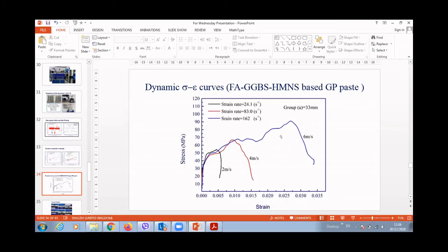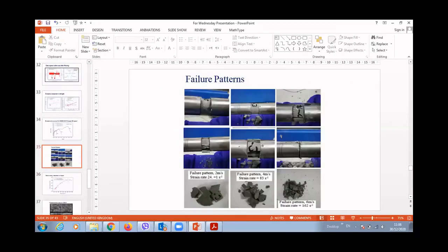To see this in reality, we have captured pictures, because on each test we have a camera to capture the samples and the impact. At different impact speeds, we found that the samples crushed from big segments and big fragments to smaller and finer ones when the speed increased. And when speed increased, we found that the strength has a sensitive relationship with strain rate.